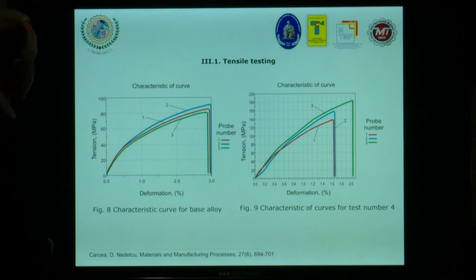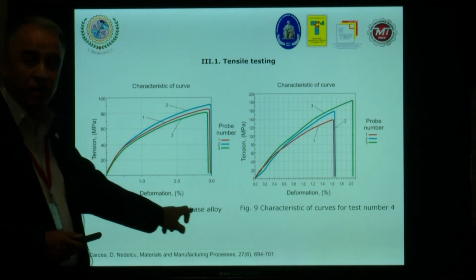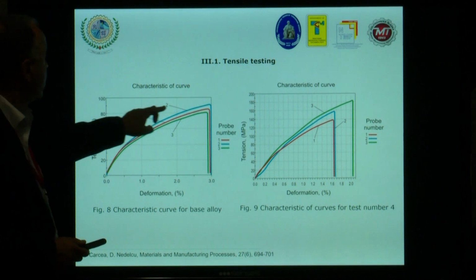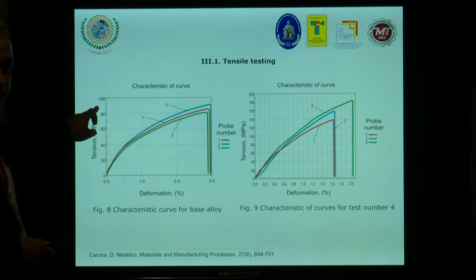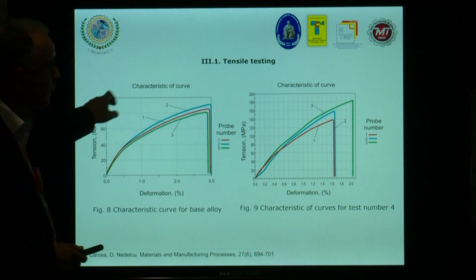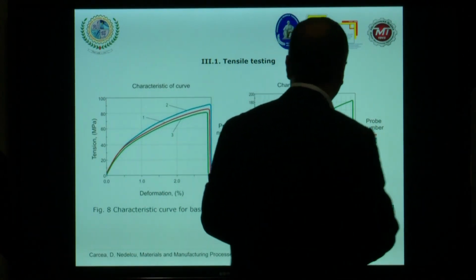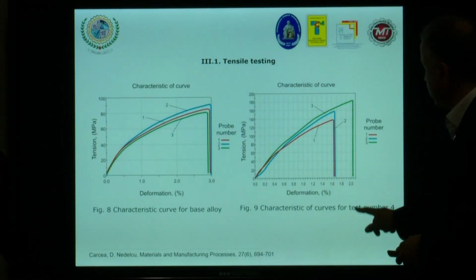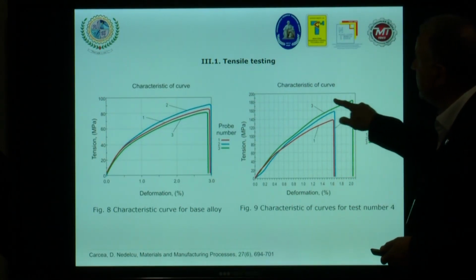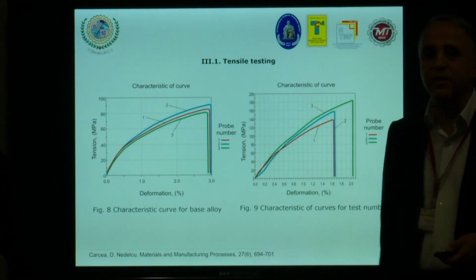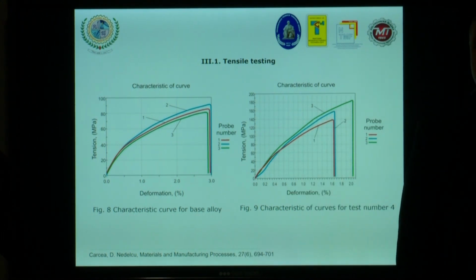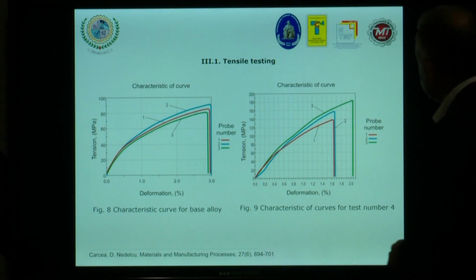You can see the characteristic curve for the base alloy. Look here, it's around, let's say, 90 megapascal. And if you go further, in the case of test number 4, you can see that it's more than 180 megapascal. So more or less, it's double as a value.